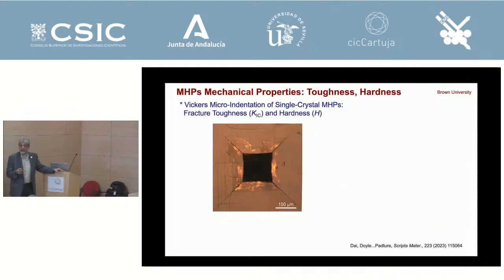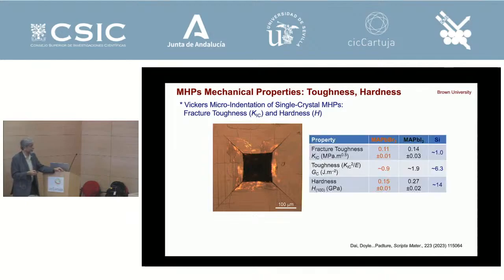And then we measured toughness. So indentation is very familiar to everybody. So toughness is on single crystal. And so the toughness you can see, these are depressing numbers. This is 0.1, this is 0.14, silicon is 1, something like titanium is 50, right? And so these are not very encouraging numbers. And this is in terms of energy. And then the hardness also is very, very soft. They're like salt. These are salts, right? They're halide, like table salt. You can crush salt very easily.